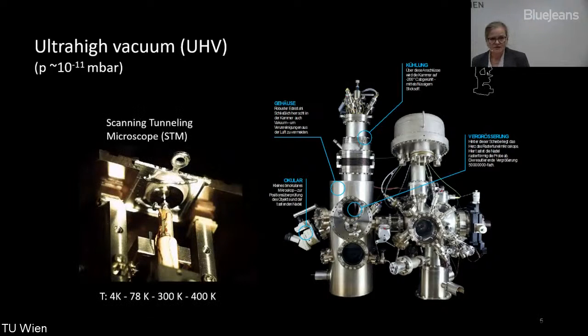The other thing is that one uses single crystals, and the method of choice, especially for metal oxides, is scanning tunneling microscopy. Here this would be a platinum 1,1,1 single crystal, and you see the end of the tip of the scanning tunneling microscope and its mirror image on this highly polished platinum single crystal. Together, one can get really nice insights.